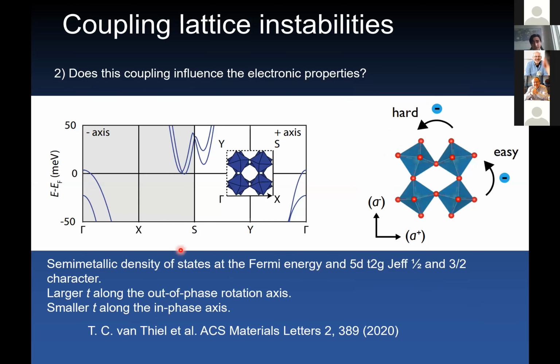And now the second question is, how does this influence the electronic properties of the materials? Well, DFT calculations indicate something very interesting. So you start from a semi-metallic state where you have a mixing of J effective 1/2 and 3/2 electrons and holes. And this creates a situation in which you're very sensitive to the distortion that you have in the system.